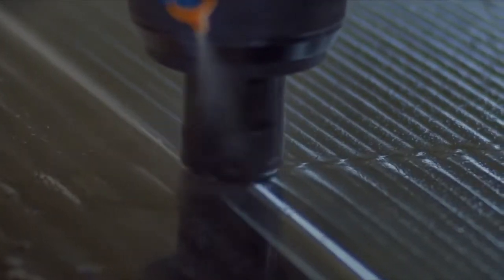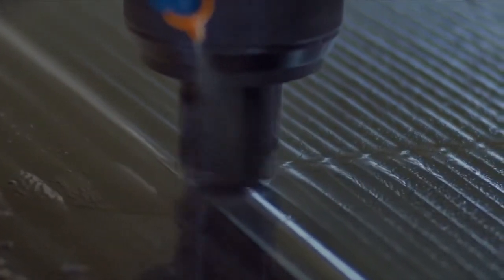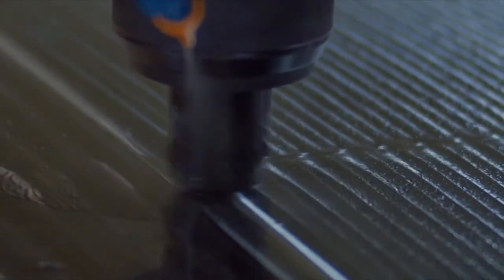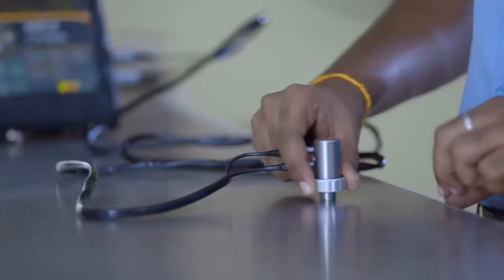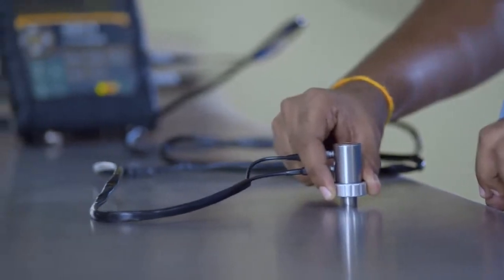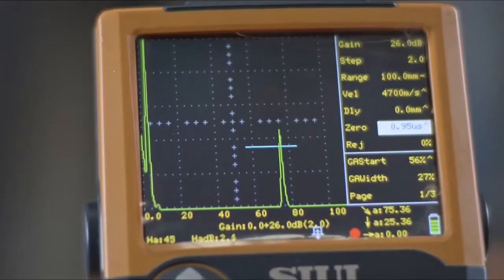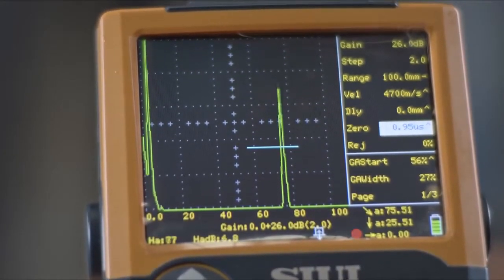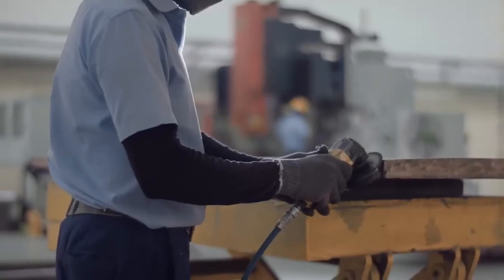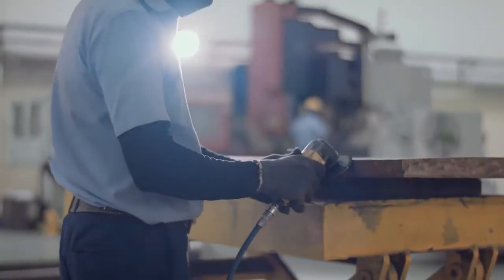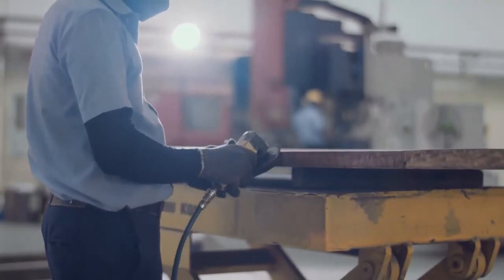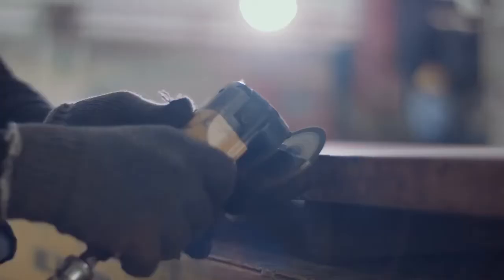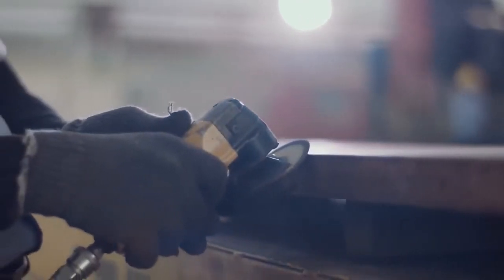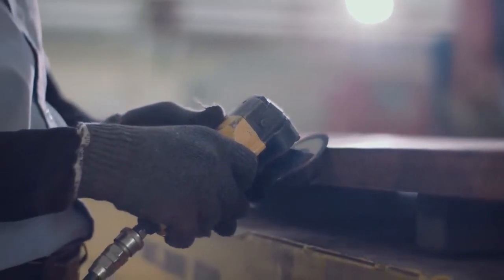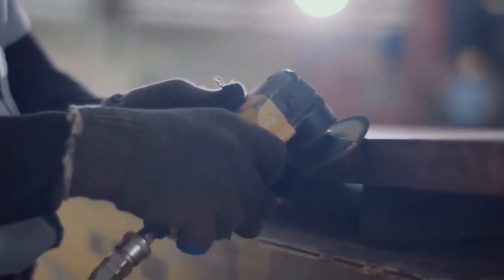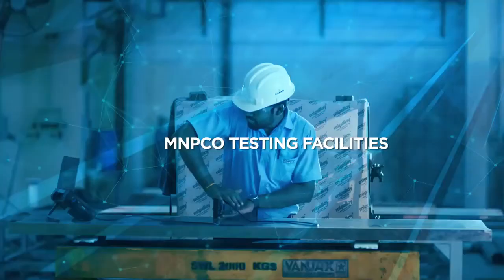After completion of machining, the mold plate again moved to buffing section for finishing operation. An ultrasonic test is performed to check for plating adhesion and bonding. After chemical cleaning, the mold plate is taken for finishing. Cold face, including the cooling slots, are thoroughly buffed. The hot face and side face are again buffed to achieve a very fine finish.